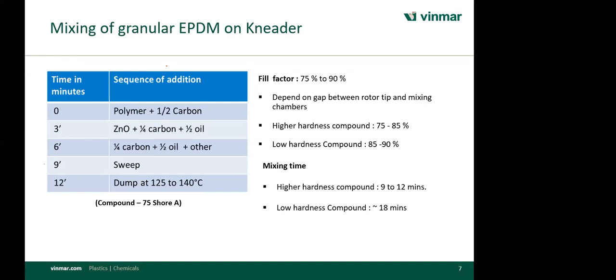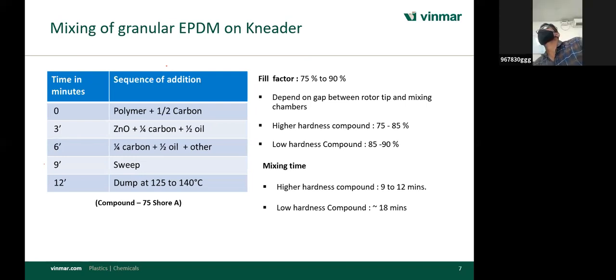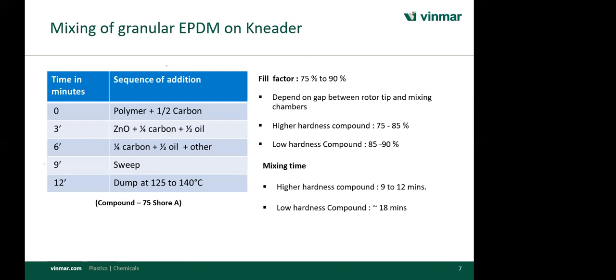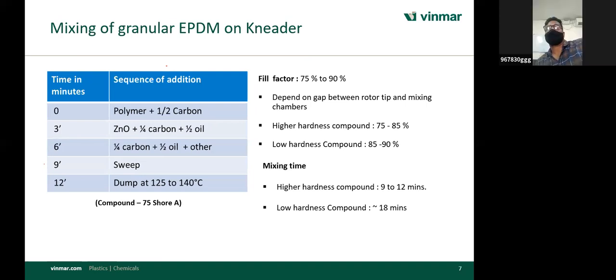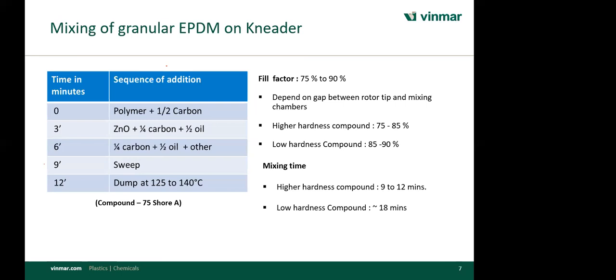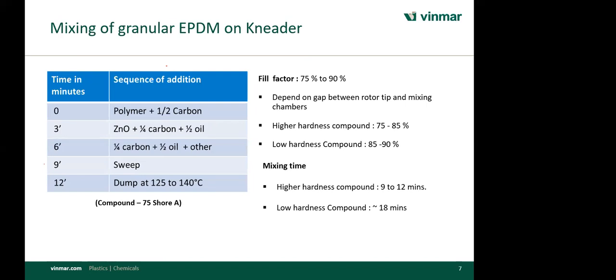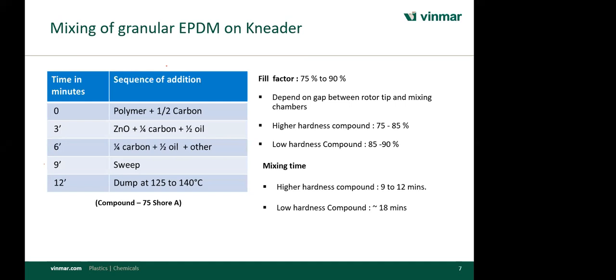Here what happens is the rubber and the filler undergo surface adsorption interaction, and it improves a lot of physical properties. I can tell you, you will get an enhancement of the properties of about 15 to 20% if you follow this cycle. After 3 minutes, you add 1/4 of carbon and half the oil, and after 6 minutes, again balance carbon, balance oil, and all the fillers, and sweep it and dump it. The recommended dump temperature for EPDM is 125 to 140 degrees. Fill factor is one of the